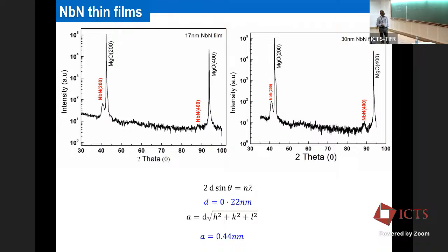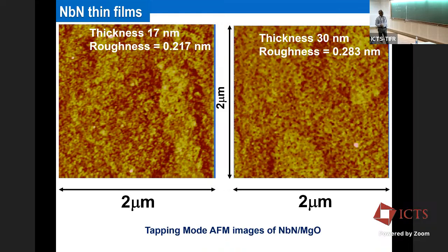So this was the characterization, and this the lattice parameter 0.44 nanometer, clearly indicating that I'm making this cubic phase of NbN only. And this is 2 micron by 2 micron scale. We are having this roughness. So roughness is around 0.217 nanometer, which is more or less equal to the roughness of my substrate MgO. So I'm having quite uniform thin film deposited onto the MgO substrate.